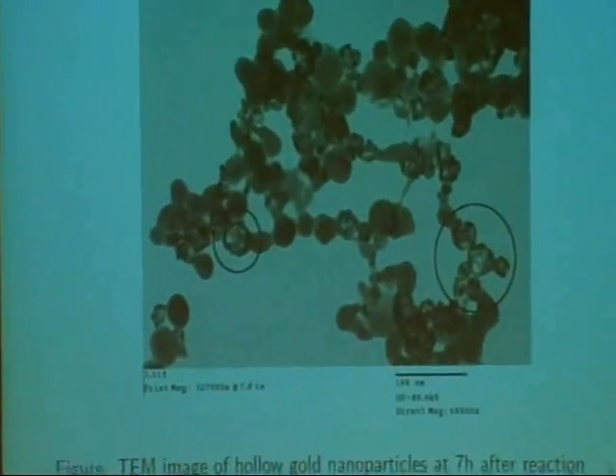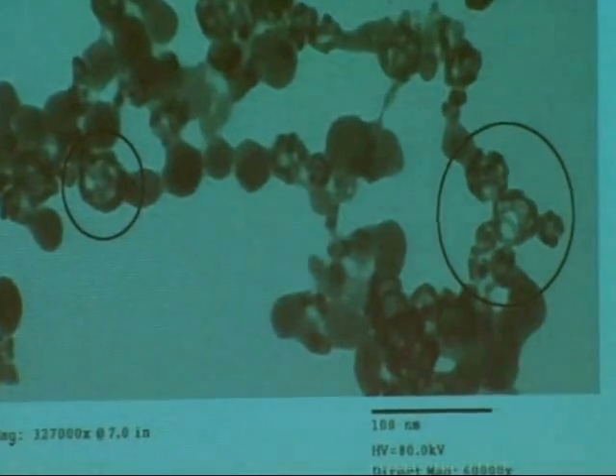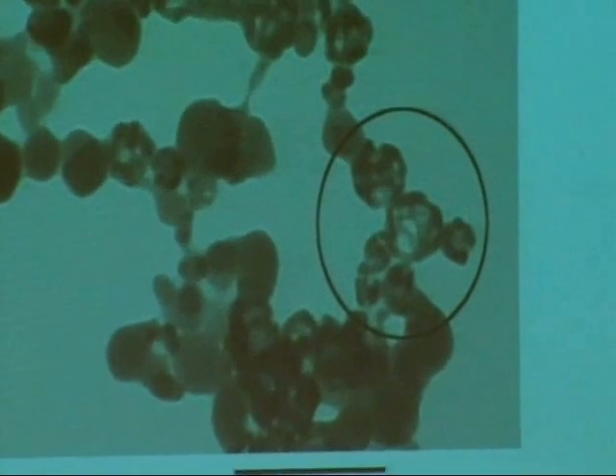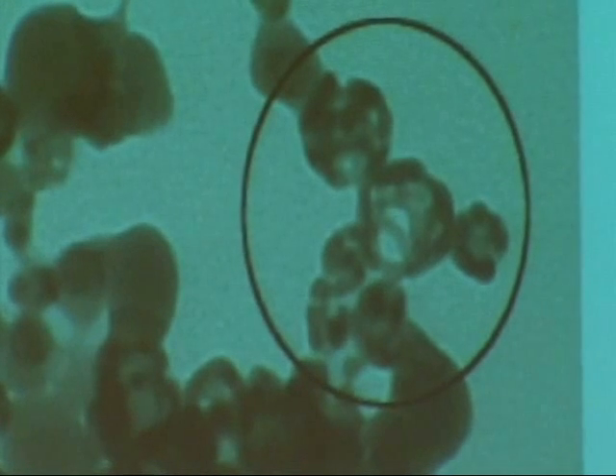Question: The images of the nanoparticles show non-perfect spheres — why is that? Well, the hollow nanoparticles would not normally look like perfect spheres because there need to be pores where the silver ions can diffuse out of the structure. As for the silver ones, there are defects in the crystallization of the silver during the reduction process. Also, at different points in the transmetallation reaction, the shape can slightly change due to gold deposition and silver dissolution, which may also contribute to the anisotropy.